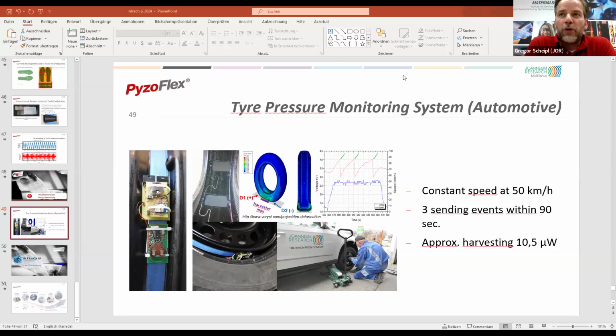If you go for spray coating or so, you might need other solvents where the PVDF-TrFE might be dissolved to have it resulting as an ink which can be spray coated. For us, this approach or other coating techniques are not in the focus. I don't know if Arkema Piezotech are also selling these inks, or if you just can source the powder, and this is of course possible, and try to formulate your own ink in order to make it processable for other coating processes as well. So it might work. We have achieved the best results and this high yield really by printing.